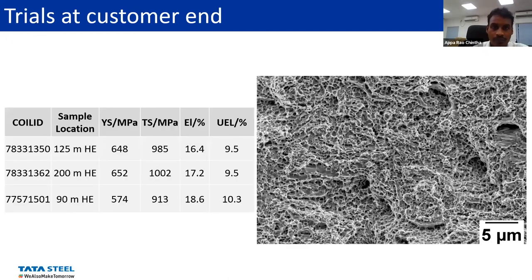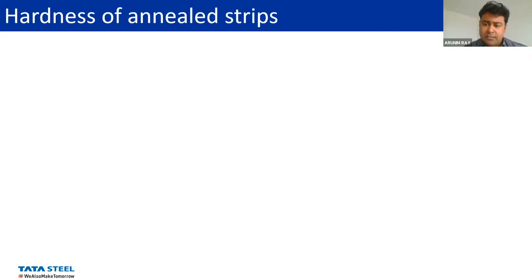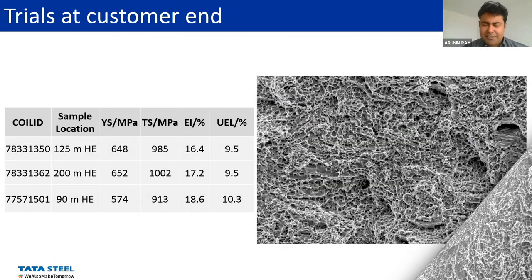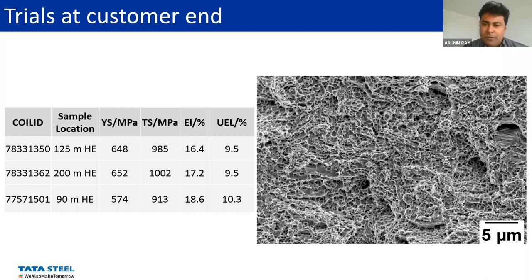There is some anisotropy, but not sure what its role is because the strips have to be slit along the length of the coil. Those variations are inevitable in strip cases. This is an interesting observation — typically this kind of controlled thermomechanical processing at temperatures lower than TNR is done to increase strength and toughness of the final product. But in this case it is kind of reverse: when rolling below the TNR temperature, in the final product the strength is decreased because of the spheroidization.